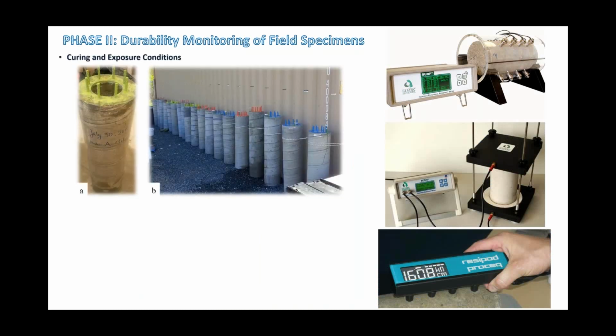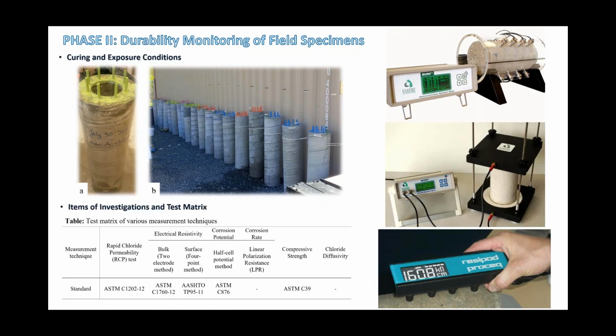25 samples. These 25 columns have a 4 feet height, a 12-inch outer diameter and a 6-inch inner diameter. 18 of them had different cover thickness of the rebar and different exposure. Some of them are exposed to the salt solution and some are not, and in some I was able to put the admixtures inside the mixture. I cured them for 14 days, and then I exposed them to the natural environment outside our civil material facility. I started monitoring these samples in 2015, and since 2016 using several different non-destructive techniques.